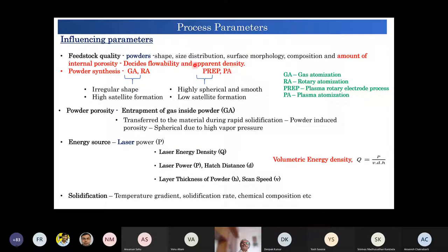Then there are other plasma processes, which are a little complicated and used only for selected materials like titanium alloys and other things, where gas atomization and rotary atomization are not suitable ones. So there the plasma rotating electrode process and plasma atomization processes are used. Here one can get highly spherical and smooth powder and a low extent of satellite formation, and this is an expensive proposition, so that adds to the cost of the process.